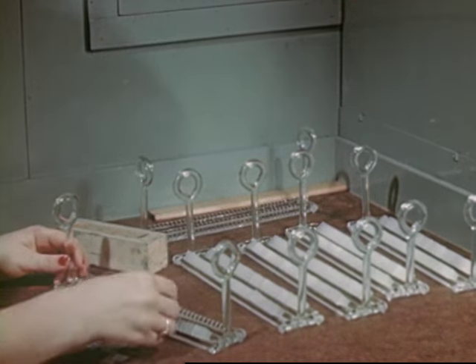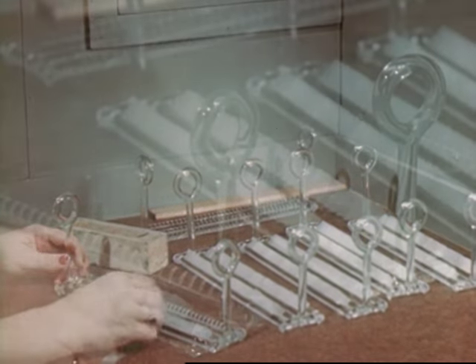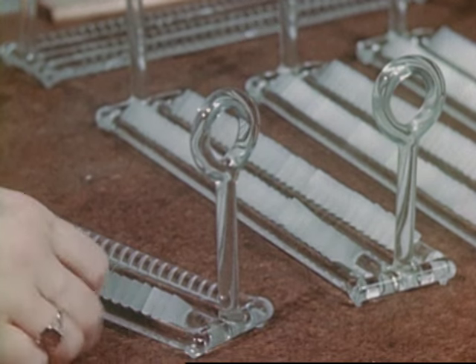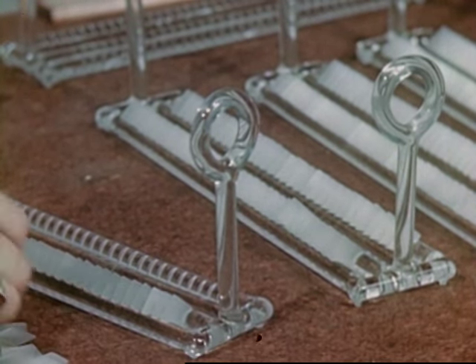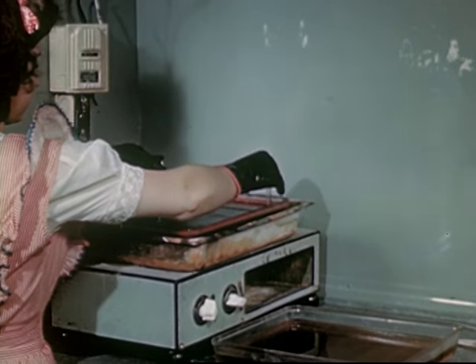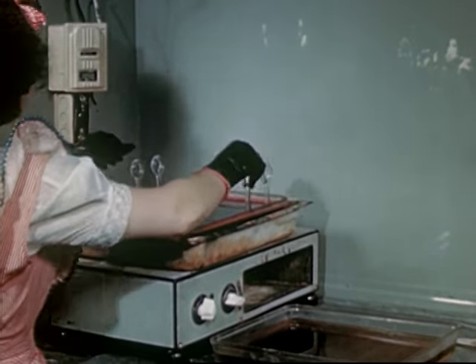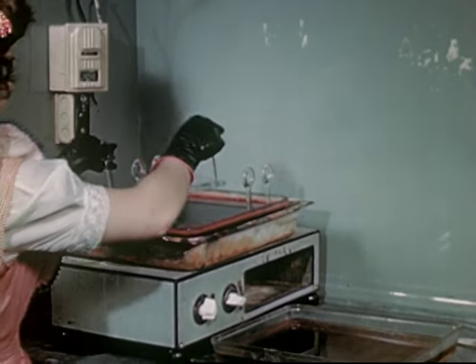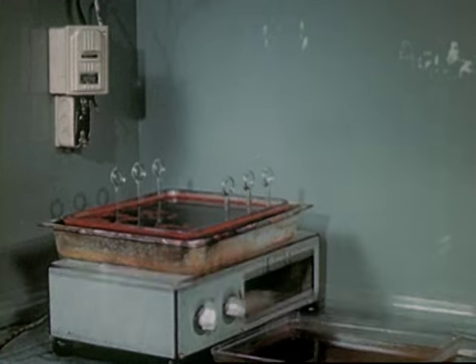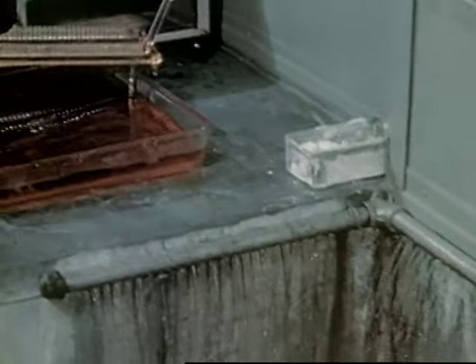In the final finishing department, the crystals are etched, first in mass and then individually by hand, to bring them up to the various specified frequencies. Preparatory to the mass etching operation, the crystals are stacked in notched Pyrex glass racks and are given a final cleansing in a concentrated chromic acid solution. The crystals are first thoroughly cleaned to remove abrasive and oil left by the machine lapping process. The racked crystals are transferred into successive shallow tanks in which the acid is washed off.